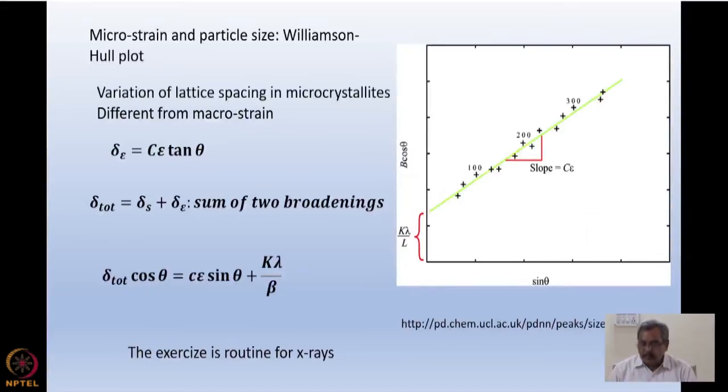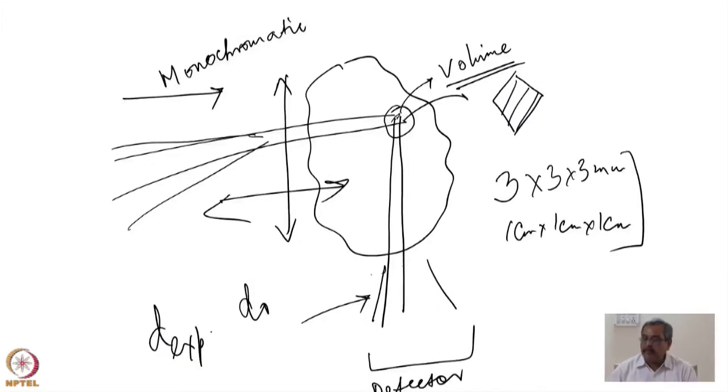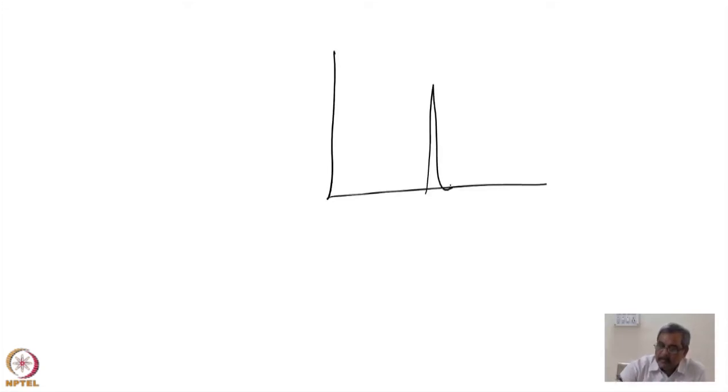Also, there is strain-related broadening. Here the strain-related broadening is not a macroscopic broadening, but here there are defects, vacancies around the site, and also there can be sometimes stresses due to a grain boundary. So here again the Bragg peak keeps shifting because there is a microstrain, that means somewhere it is elongational, somewhere it is compressional, and this Bragg peak gets broadened due to this microstrain.